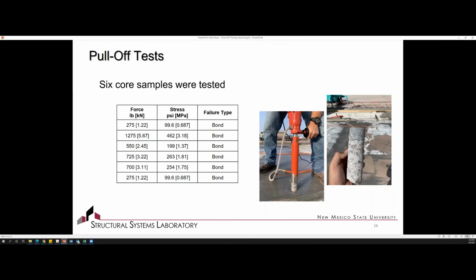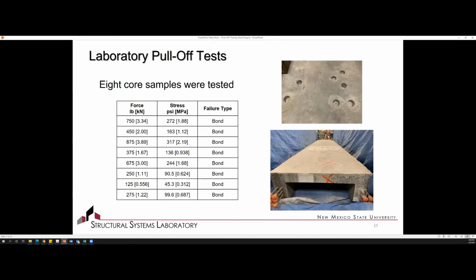So we also did the pull-off test. We went out and poured several specimens and did some pull-off samples. We tested this and looked at the bond behavior of that. Some of the cases were a little bit lower than what we wanted to see with the field, so we went back and did some laboratory tests as well. With the laboratory tests, we were able to identify really key elements that were causing us issues in the field so that we could address those issues, work with the contractors and the New Mexico DOT to make sure that we get the bond that we're looking for.